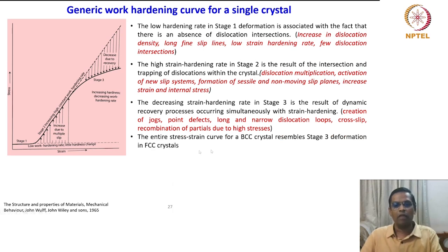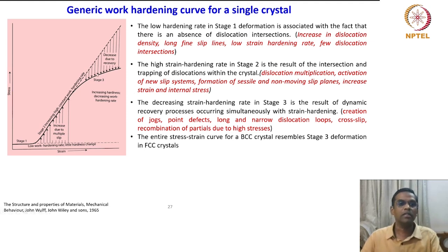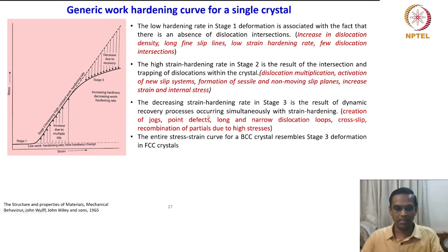The entire stress-strain curve for a BCC crystal resembles Stage 3 deformation in FCC crystals. The Stage 1, Stage 2, Stage 3 behaviour we have seen is for the face-centered cubic crystal system. For a body-centered cubic crystal system, the entire curve will look like Stage 3 only — a very different kind of work hardening behaviour is exhibited by BCC materials compared to FCC materials.